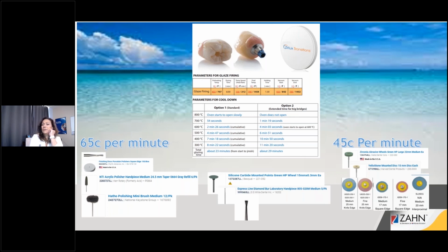Not that you should need to, because if you've designed properly, you shouldn't need to go back in and redefine secondary grooves or anatomy. But if you find yourself needing to, an inverted cone is always a great choice for that. And all of these tools would work great on the Zirlux Transitions or any product. And then also very important, after the zirconia is sintered, you want to make sure that you're using the proper tools to contour it, to seat your contacts, adjust your occlusion. One of the things that we don't realize when we're grinding on zirconia is with the wrong tool, you can generate a lot of heat. And although zirconia is very strong, the one thing that it is susceptible to is thermal shock.